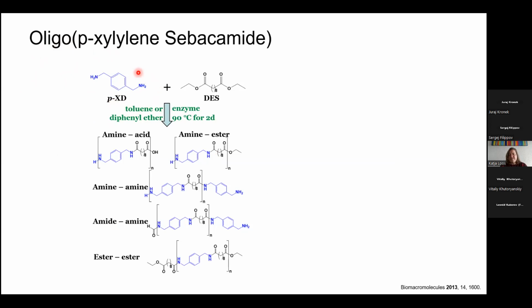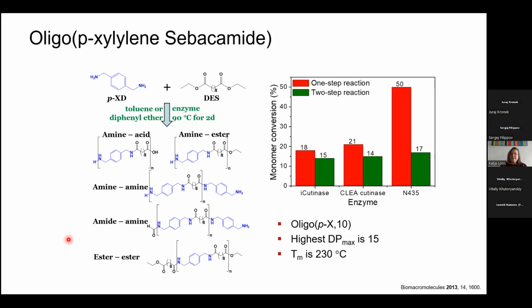But actually, these extremophiles like CalB, they really don't care. So if you have an aromatic diamine and an aliphatic diacid, it really works very well. And I already told you that we are always looking for the end groups, and of course the molecular weight and dispersities. And you really see that you have a very low molecular weight, but this one already has a melting point of 230 degrees Celsius. And so you're coming into the range of high performance polymers already with a degree of polymerization max, so the average is a lot lower.